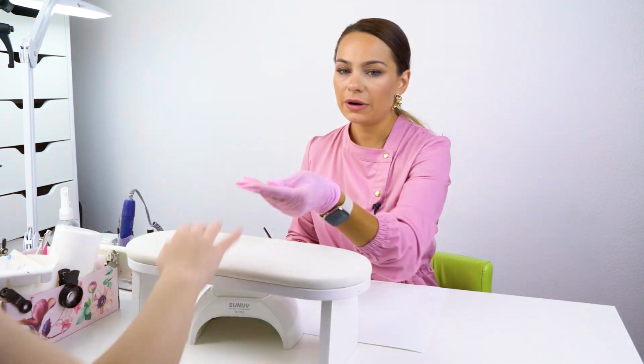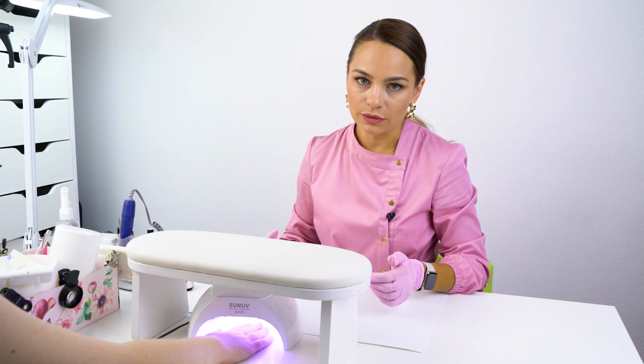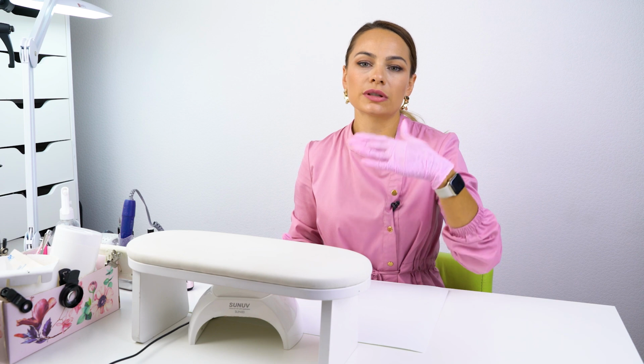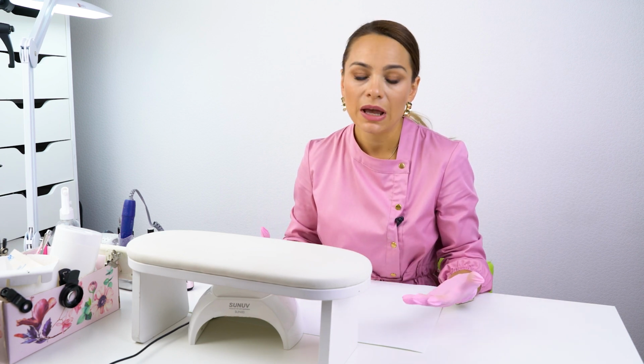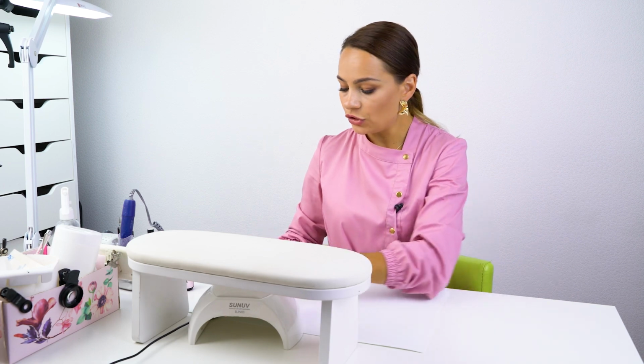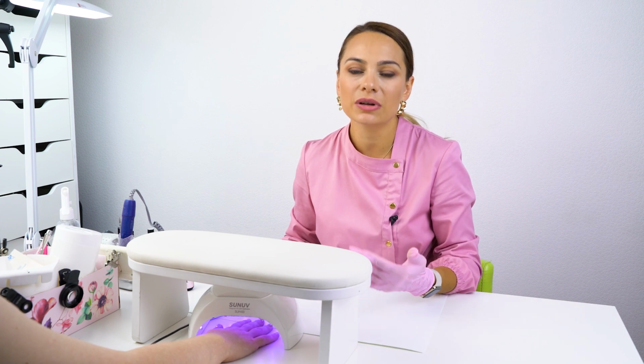That's why we need to take such tests from time to time, to make sure that our lamp works properly. I send the nails to cure. When the molecules bond, they release heat, and your client may feel burning and take the hand out. Then the polymerization reaction stops. And though the top part has cured, the layer is still wet inside, which then results in liftings. In this case, we may turn on the low power mode, so that it doesn't burn that much while curing. And in no way should we tolerate burning, since it will lead to other negative consequences.